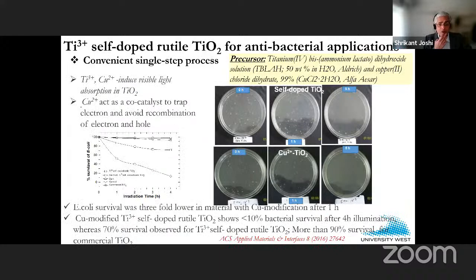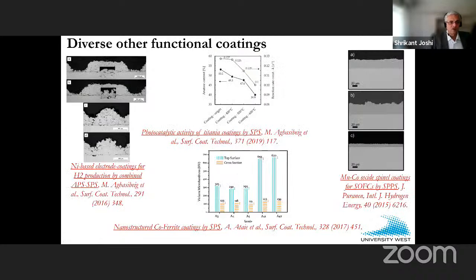This is similarly some work that I did before moving to Sweden, and this was to target some antibacterial applications using solution precursors. I mean, very complex precursor. If you have good friends in the chemistry lab and have a beer with them, it helps once in a while, right? But it gives you coatings of a nature that are very hard to achieve by the powder route, right? In this case, the intent was to achieve Ti3+ self-doped rutile. And the chemistry guy said, you use this and you have a good chance. And sure enough, we did get coatings which showed extremely promising antibacterial performance using those kind of complicated solution precursors.